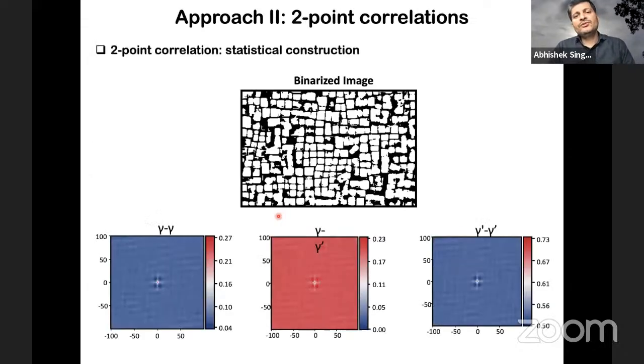The second approach was a 2-point correlation based approach. We have these binarized images, then we have a gamma-gamma correlation, gamma-gamma prime correlation, and gamma prime-gamma prime correlation, but any one of them is good enough. So what we do is take a white pixel here, then we try to find out the probability of getting another black pixel in the entire image. The size of this chart depends on the size of your image. In this case it's 40,000, but if you have very high resolution images, it can go to the millions. So the number of features is suddenly very large, and we obviously cannot work with such a large number of features.